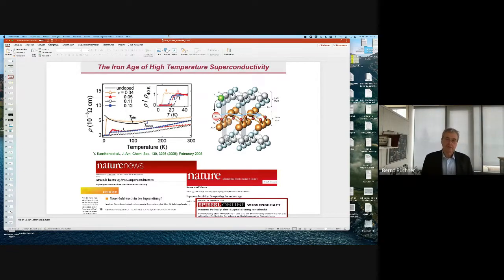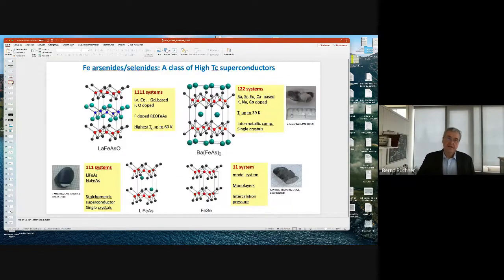So people hoped that we really can come to higher transition temperatures. And of course, there was also the question: what is the mechanism? Is it a new mechanism? Is it an unconventional superconductor? Till today, there are a lot of efforts on that. There are many examples, meanwhile, of these iron-based superconductors, and that's just a couple of the most prominent ones. You see these are the systems where superconductivity has been discovered. The characteristic feature in all of these systems are these layers here. We have iron arsenic or iron selenium layers in a tetrahedral environment, which we will have a closer look at later on. And in the initial compounds, between these iron arsenide layers, there were these lanthanum oxide layers.